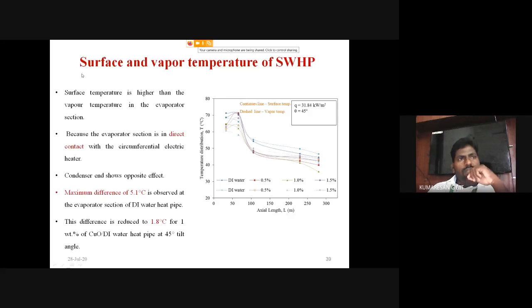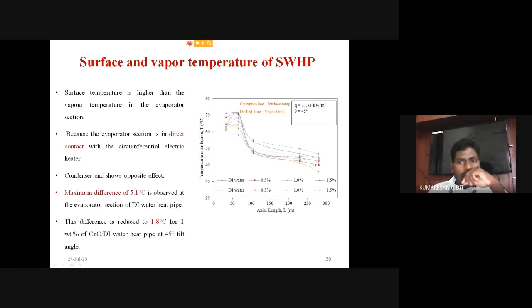The first one is the surface and vapor temperature comparison of the SWHP, the sintered wick heat pipe. You see here that the vapor temperatures are somewhat lower than the surface temperature at the evaporator section. But in the condenser section, the vapor temperature values are higher than the surface temperature. Because in the evaporator section, the heating device is in direct contact around the circumference, the surface temperature of the evaporator section is higher than that of the condenser section.